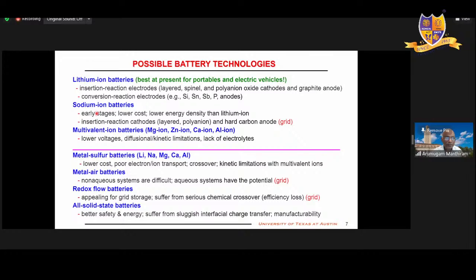How can we suppress it with molecular engineering by substituting tellurium? You can change the lithium deposition morphology from this ugly thing to this much smoother one, and that is also reflected in better cyclability. So this is again chemistry. If you do not put any tellurium, your cyclability is like this. As soon as you put 10% tellurium, it substitutes into those polysulfides to form lithium polytellurosulfide. That forms a nice protective layer on the lithium metal anode. Then that gives you good cyclability.